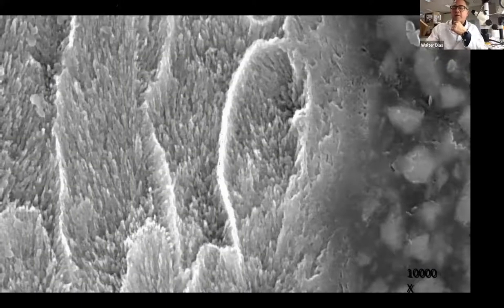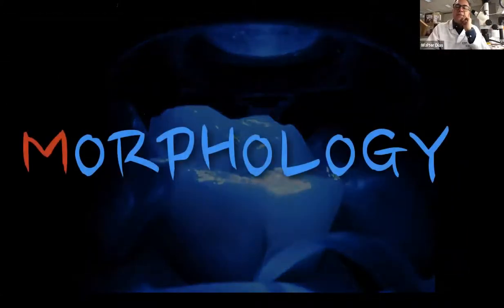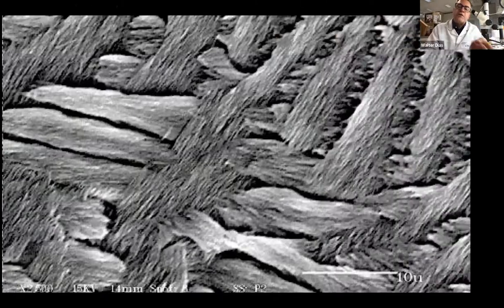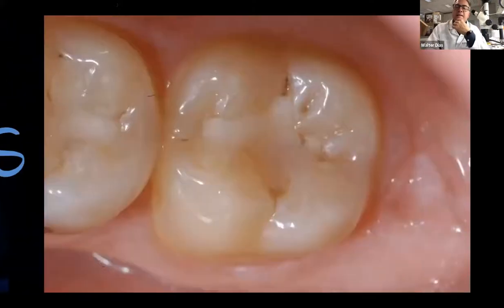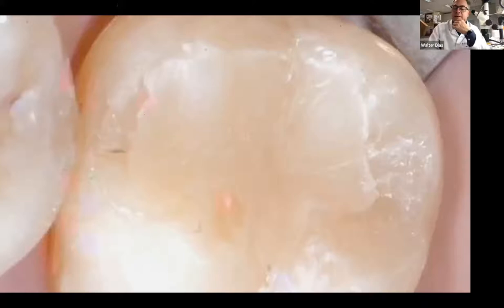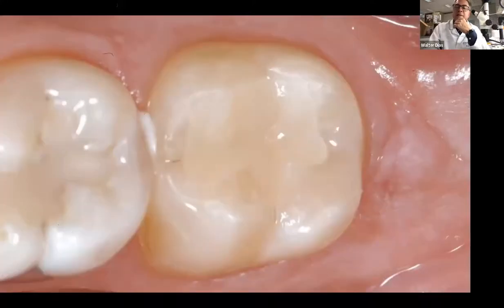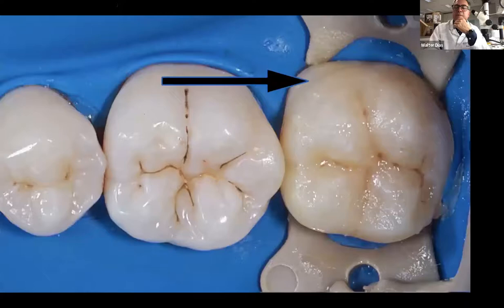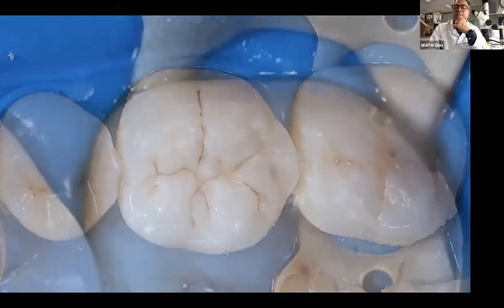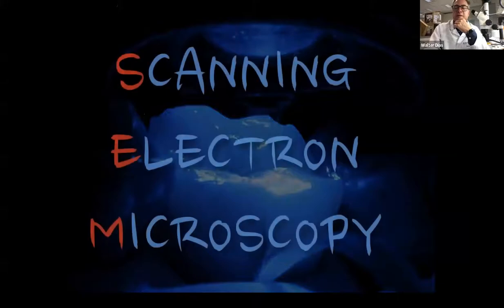Here, what you see is an interface of the adhesive bonded to the composite on the right, and the enamel and the enamel rods on the left. This is a seamless transition between the enamel and the cement. But what you can have sometimes, due to the morphology of this enamel, all this is enamel, depending on the angle, you can have these white lines. Let me show you a case where you see these white lines. And these white lines, here I show you another case. Right there, you can see these fracture lines.